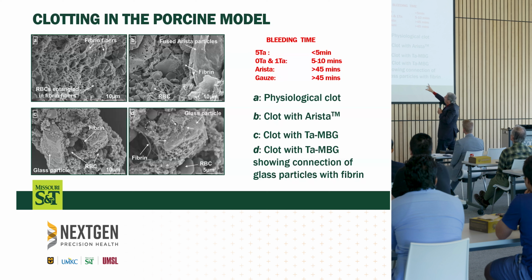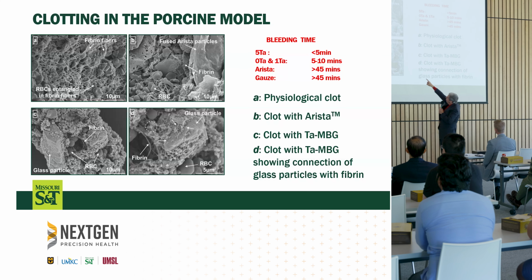Well, let's look very quickly at the top of picture B. We see there particles of the Arista. Those are the big kind of bright particles there. And we see the first instances of an early clotting reaction. We see those fibrin chains, and we see these RBCs, red blood cells. What we also see is those red blood cells and those fibrin chains aren't interacting with the Arista particles. They're not growing on the surface. They're forming a clot, but they're forming it almost despite the Arista particles, not because of it.